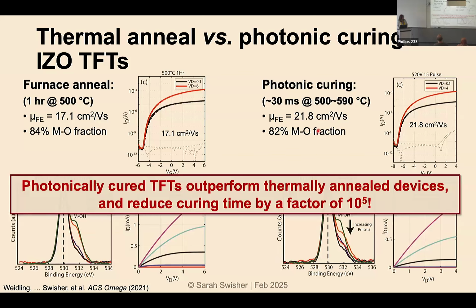That's something that we are still working on, because right now we can take the material to about 500, 590-ish degrees when we do this on glass, whereas when we have a plastic substrate, we find that the failure of the gate dielectric typically limits us to about 350 to 400 degrees. So that's something that we're still working on.